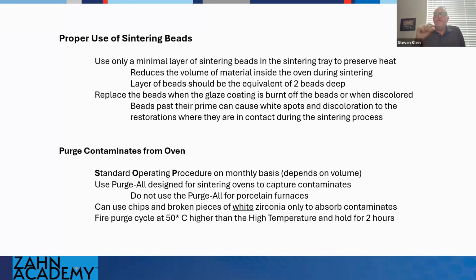If you were able to stack those beads one on top of another, you would want to do about 2 beads depth. That's it. 1 bead on top of the other, and don't pour it halfway full into the tray. That's not necessary, and that is way too much. So keep the bulk down, put the units in, and you're good to go.